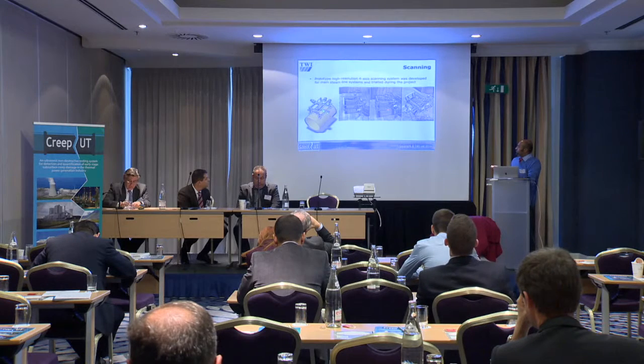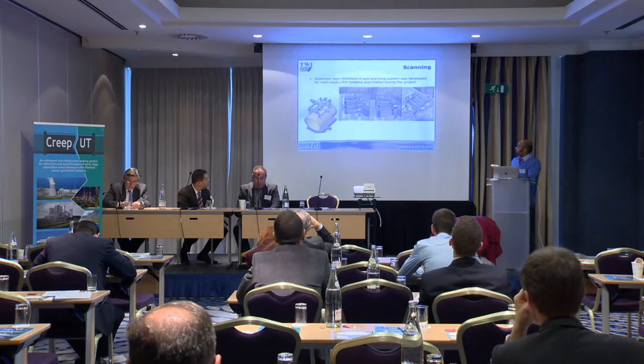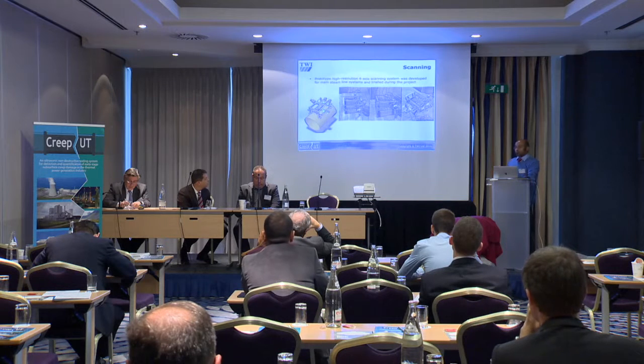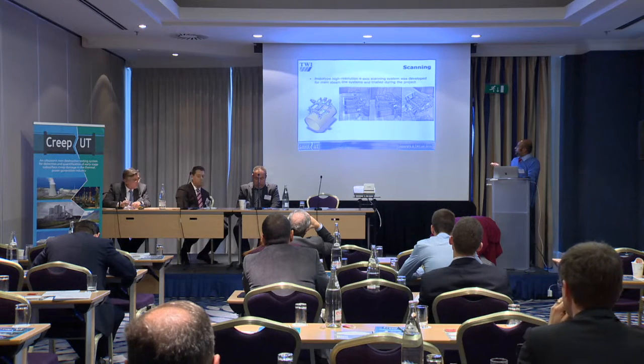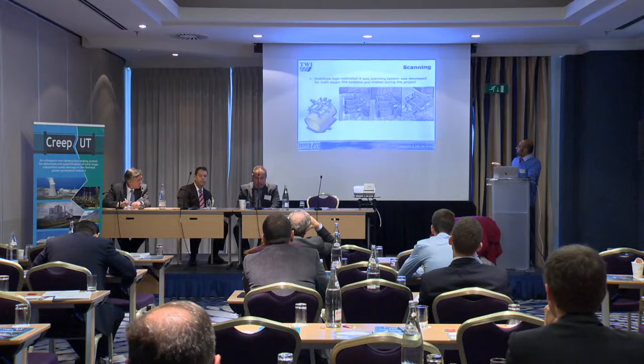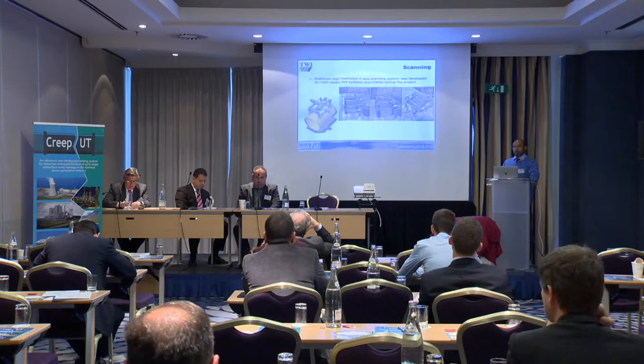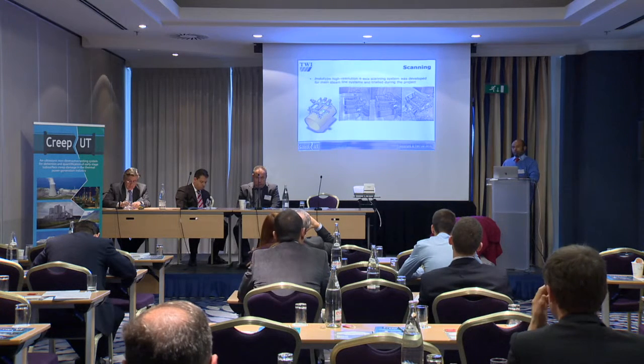So this is a prototype scanner that we developed, which was essentially an R&D scanner, and it was expected to be as such. It was not really configured for site work, though it could have been taken on site. This is a piece of steel that was provided by SSE, into which we put some targets, some calibration targets for setting up the scanner. And you can see the rough dimensions, and it was quite a large, chunky scanner, but able to operate two probes in order so that we can explore different